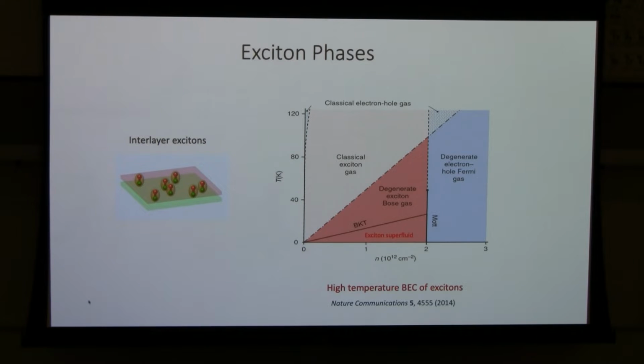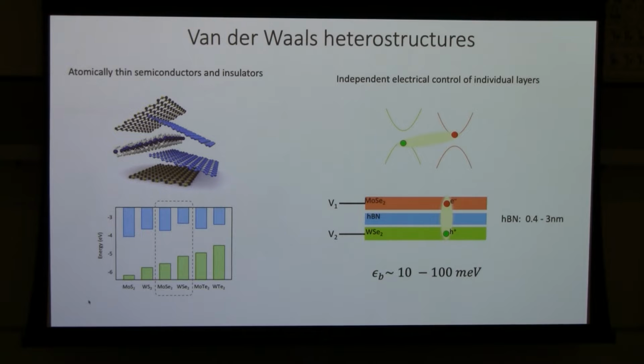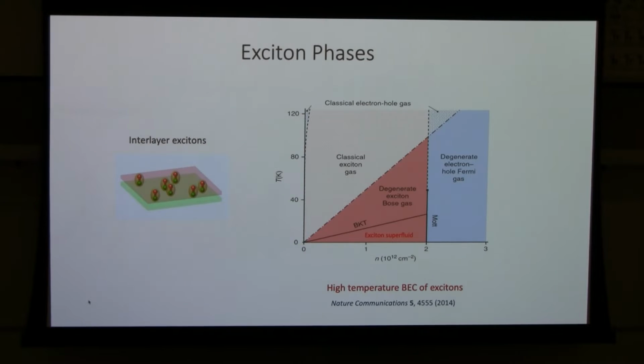So with this electron-hole bilayer, theorists were always ahead. They predicted many interesting phases that can emerge. If we create a situation where the electron and hole charge densities are exactly balanced, then the electrons and holes can form tightly bound excitons. An exciton is a boson. So with this boson, if you go to very high temperature, you basically have a boson gas. They can last to 100 Kelvin. You have this tightly bound exciton gas.